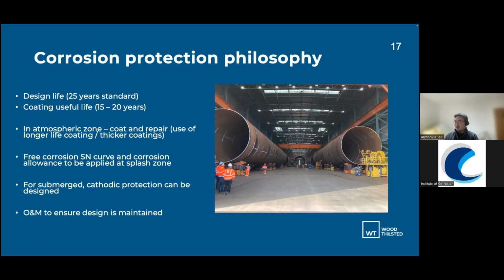So what do we need to do here? The standard design life at the moment is 25 years. However, when we go to the coating useful life, if you follow the DNV standard, we're looking at 15 to 20 years only. So what do we do next? Beyond that, we have to consider making sure that we can repair the coating. We inspect and repair in the atmospheric zone. In the splash zone, it's a bit more difficult to inspect and repair. Therefore, we have to include what we call a free corrosion SN curve, which is the fatigue curve, as well as adding corrosion allowance. So that's quite a lot of penalty, let's say for 5 years.